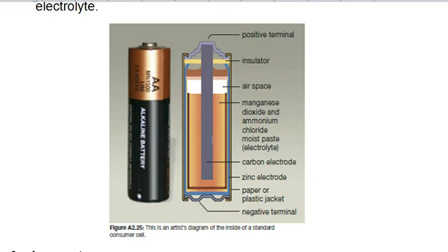And so these oxidizing agents are gaining electrons, causing electrons to leave the zinc casing, go all the way around, and be gained. The reason that your battery doesn't burst open, or shouldn't burst open, is that you have fewer ions in the paste than are required to react all of the zinc. So the zinc maintains its thickness and its integrity. If that doesn't happen, the zinc casing will rupture, and you get battery stuff leaking all over the place. Because oftentimes the electrolyte is not just the two things you're seeing here, but there's also some base in there. So they're alkaline, and so you get base leaking out, and that's never good. It destroys a lot of stuff.